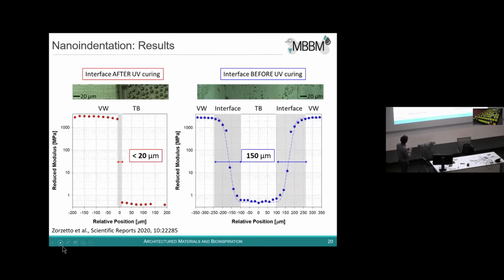So these are the properties of the interface that is formed after UV curing. One polymer is deposited on top of an already partially cured polymer. And what you see here, going from the stiff to the soft polymer, this is relative position, spatial coordinates, and you see that there is a very sharp transition of less than 20 micrometers. You have a transition between 2 gigapascals and less than 1 megapascal in properties.